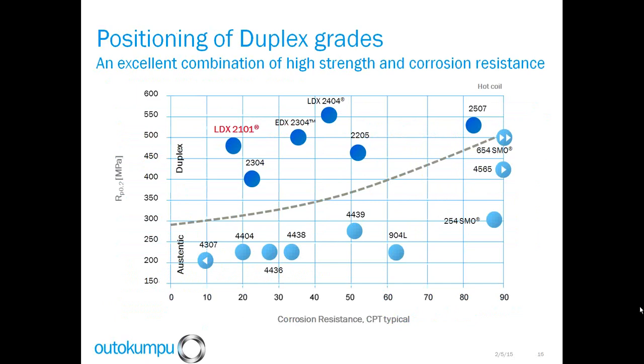The figure in this case shows the duplex grades have higher yield strength than the corresponding austenitic grades towards the bottom of this figure. You can see at any given corrosion resistance level, we're always going to find the duplex have higher strength.